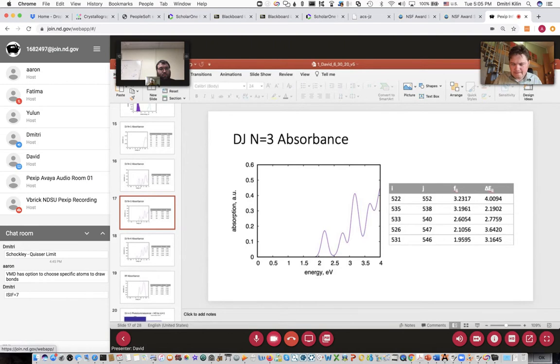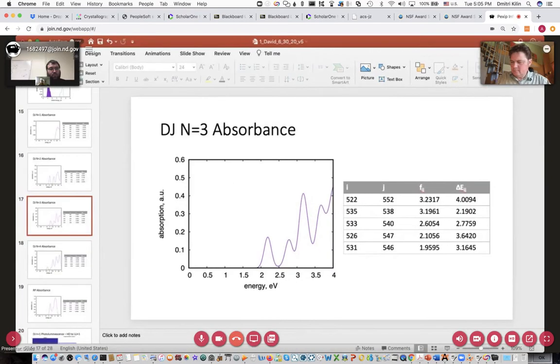Yes. Okay. And then for the dynamics, you would expect it to show up in the photoluminescence. And if one would follow the occupation of HOMO and HOMO -1, LUMO and LUMO +1, they will arrive at about 50-50 occupations, or maybe slightly different, but non-zero occupation of 2 degenerate orbitals as time goes to infinity.